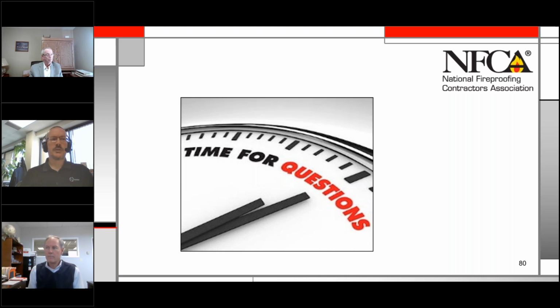In UL 1709, 5th edition, first published 5 years ago, in the annex there are some methods for allowing the manufacturer to publish thicknesses based on different failure temperatures than the traditional failure temperatures in the standard. I think this is to do with performance-based design. It lets the designer use different failure temperatures, whether they're lower or higher. I see. So there is a way to do that.